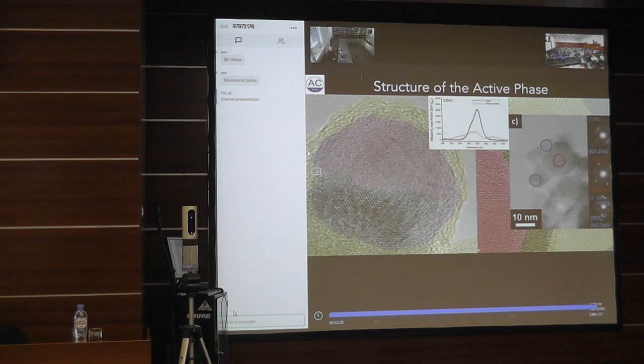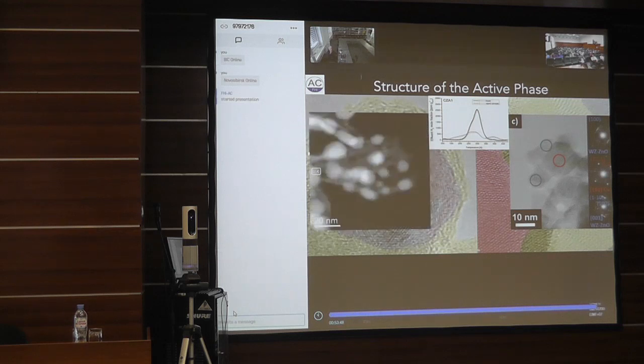So the copper particles grow larger, and when you look at the electron microscopy of this, you see that this is a different structure, because here the copper and the zinc particles interact in such a way that there is no strong metal support interaction between zinc oxide and copper. There is rather a perimeter of zinc oxide on a large copper particle. And you can also see in this 3D electron micrograph the zinc oxide support, and you see the copper particle sitting on top of it, and they form a very porous structure, and this porous structure is where the CO2 and the hydrogen are diffusing through. This is really a super high performance catalyst, and you can make it at 25 tons, and 1 ton costs about 1,500 euros. So this is a very nice artwork of nanotechnology.